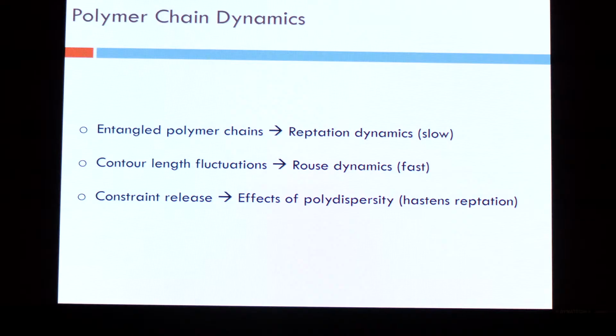The third motion is a two-body problem because it's not one chain, you have an entangled chain with it and both are moving. So if one chain is smaller than the other, this is the case here because you have a very high, ultra-high molecular weight polymer mixed in high density, which is much lower, 10 times lower molecular weight. So the tube of the ultra-high is formed by smaller chains.